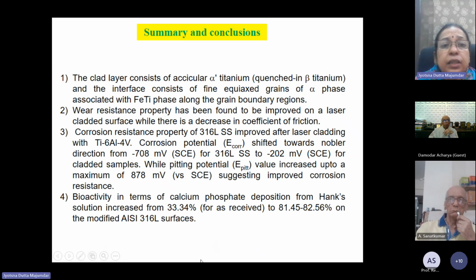So these are some of the observations. The clad layer was quenched alpha prime titanium. This alpha prime is always there when we melt Ti6Al4V using a laser beam, because of very fast cooling. The interface consists of fine equiaxed grains of alpha. In addition, there is presence of FeTi phase. Wear resistance is significantly improved. Corrosion resistance is also improved, and bioactivity is increased from 33.34% for as received to 81%.